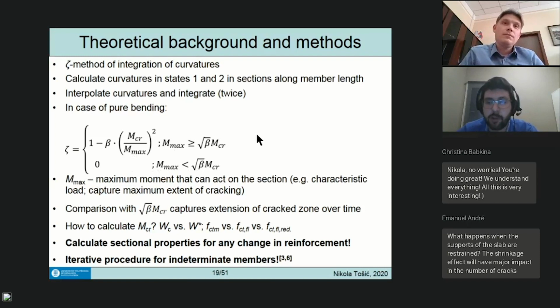So it seems as if we're not comparing with the cracking moment, but with the product of this. Why? Because if you put this beta within the brackets here, it becomes square root of beta, since here you're squaring. And that is the fact that this beta is modeling the reduction of the cracking moment.